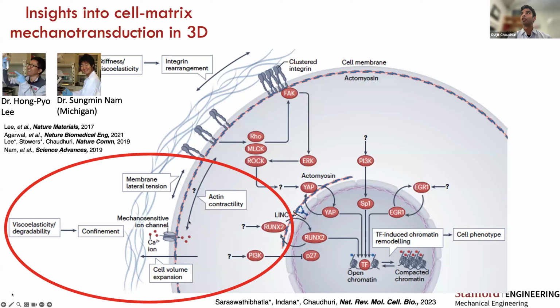And importantly, when you have a purely elastic matrix that's confining, we see that cells are often stuck and they can't change their volume. Whereas when the matrix is viscoelastic or degradable, cells are able to change their volume and activate these pathways, and in that manner are able to sense their confinement and matrix viscoelasticity.